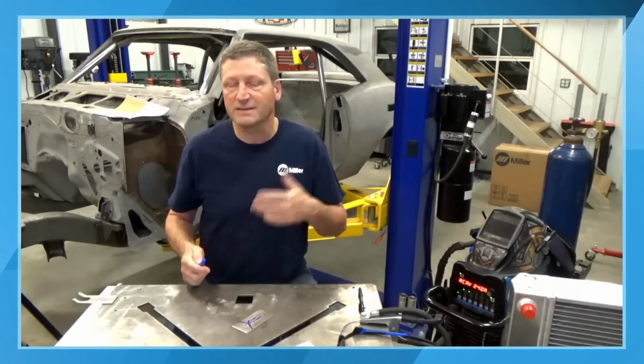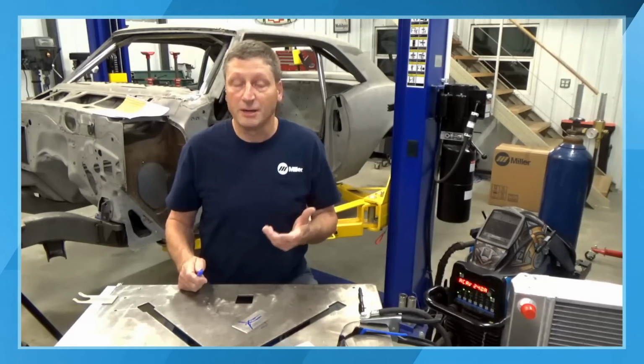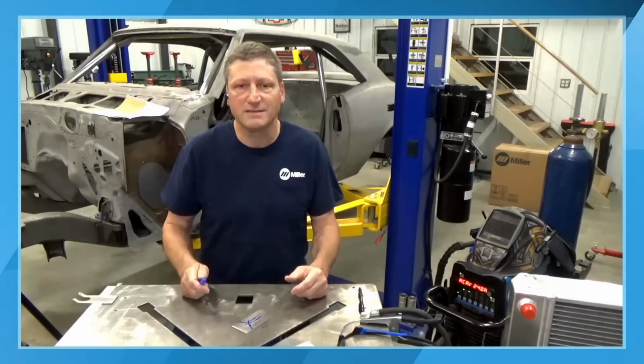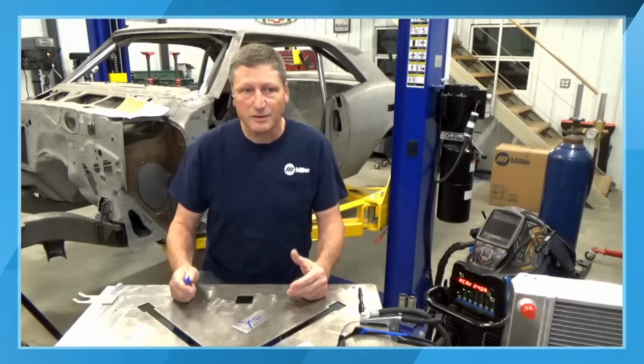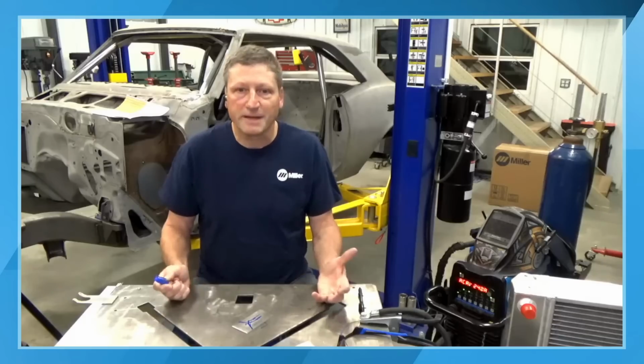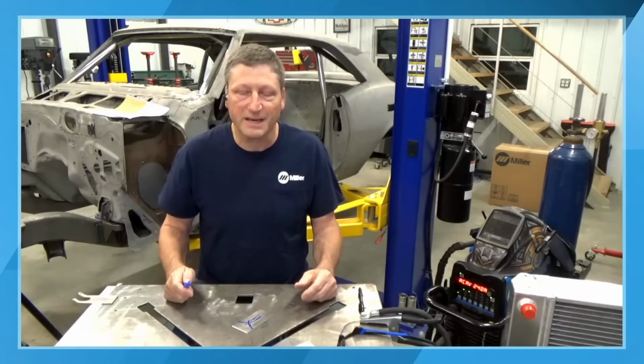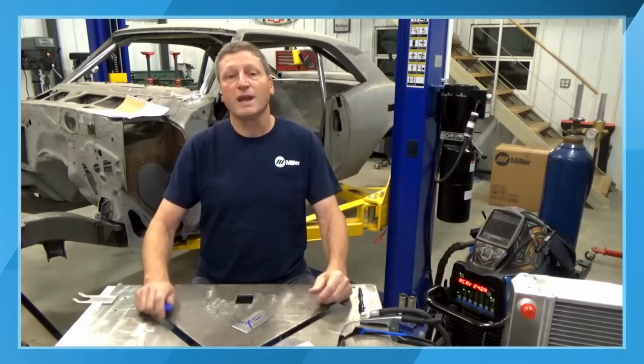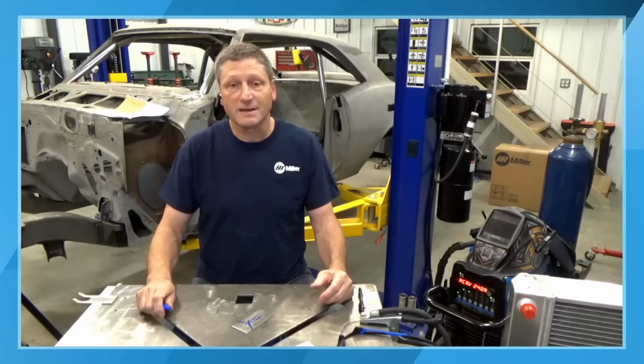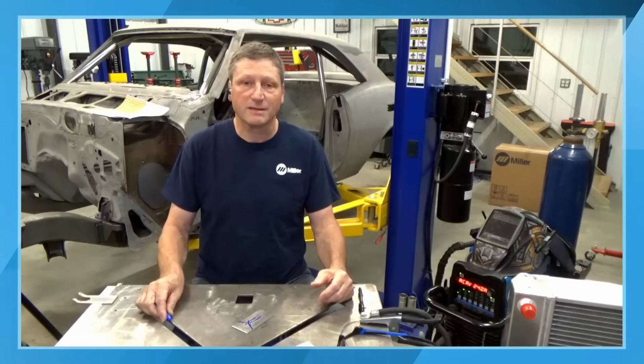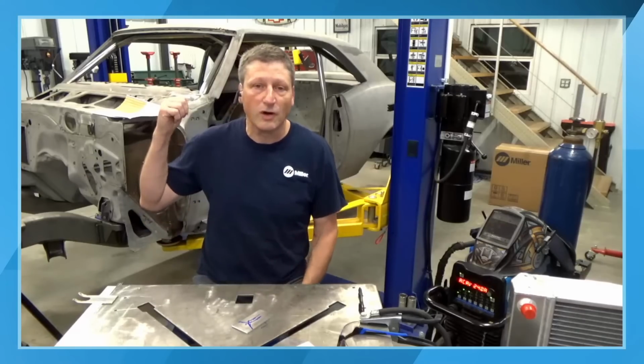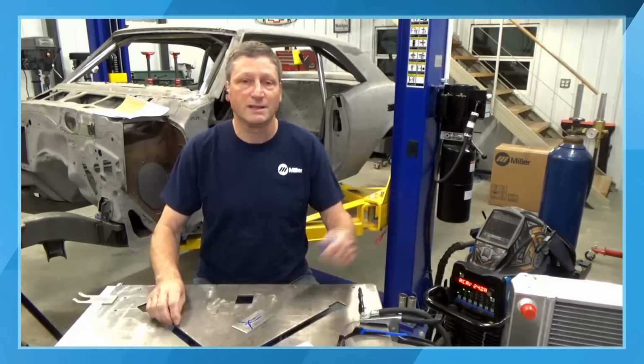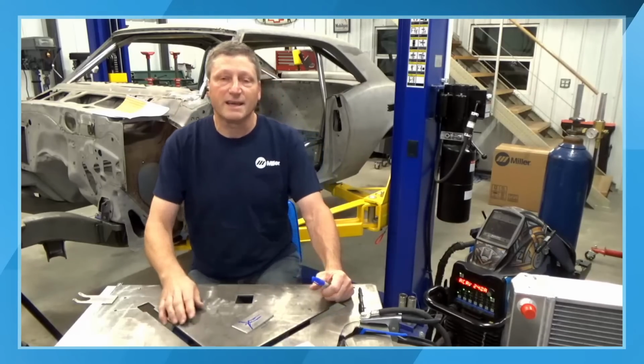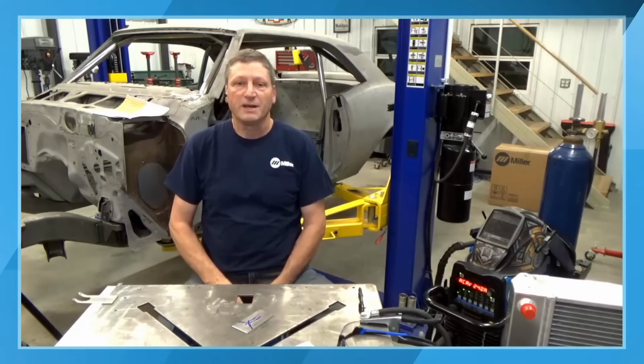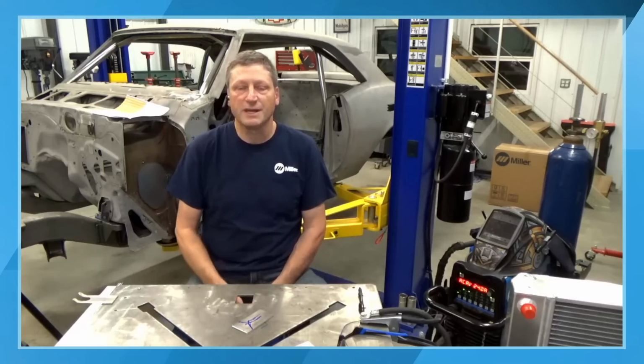So tungsten, like ceriated tungsten, is doped with the rare earth element cerium. Lanthanum for lanthanated, right? So you can get into these different blends of tungstens also. There's some companies that make trimix ones where they have three different elements in it. But for most of what I do, the ceriated tungsten works the best because I'm constantly switching from welding high strength, low alloy steel roll cages, and then I'm welding aluminum next. So I like that versatility of the ceriated tungsten. But if you primarily work with aluminum, try the lanthanated, you'll like it.